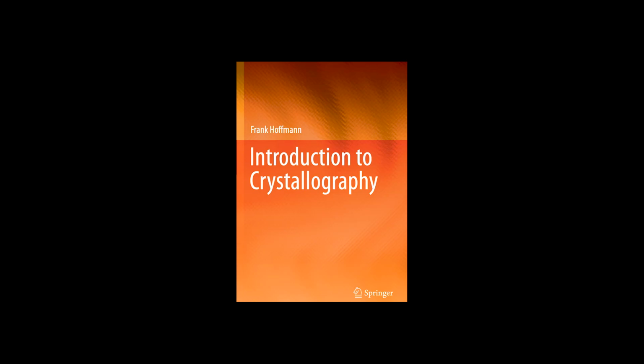It's incredibly information dense. Let's look at a really concrete, familiar example. Rock salt, common table salt, NaCl. What's its structure like in this system? Rock salt crystallizes in the cubic system, which has high symmetry. Its specific space group is Fm-3m. Okay, break that down. F stands for face-centered cubic Bravais lattice. It means there are lattice points at the corners and in the center of each of the 6 faces of the cubic unit cell. Okay, and m-3m? That part represents the point group symmetry associated with the lattice points. It's one of the highest possible point symmetries in the cubic system, involving multiple mirror planes and rotoinversion axes.